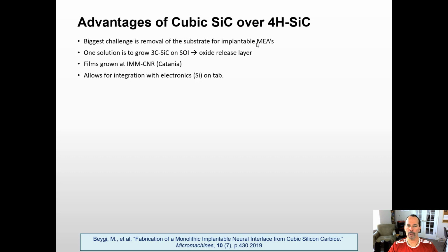I mean, almost no leakage current, wonderful performance, but it's really hard to get through the second hardest material that we know of, which is silicon carbide, to remove that bulk substrate. So one solution to this manufacturing challenge was, what about cubic silicon carbide and SOI? I've done a lot of work in my group on this over the last 20 years, and then we can use HF to simply release the device.